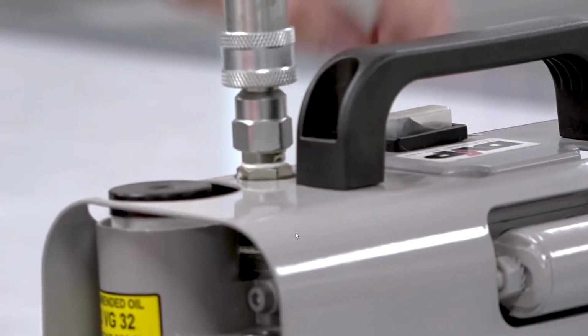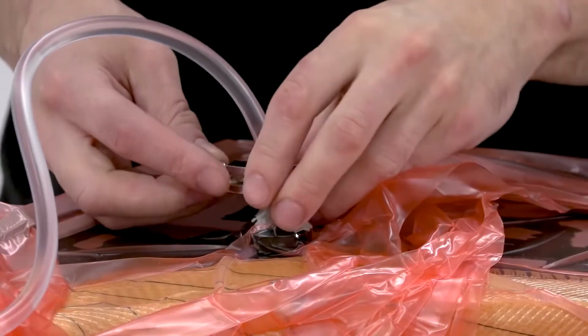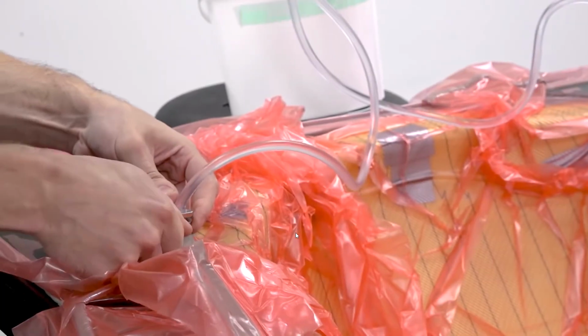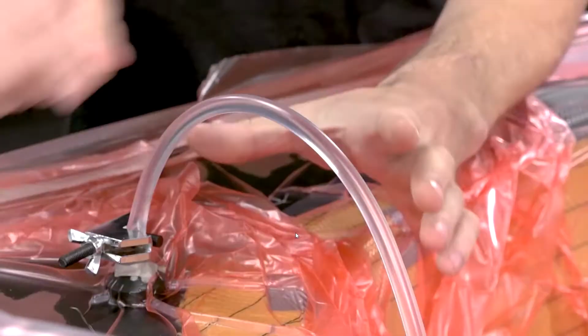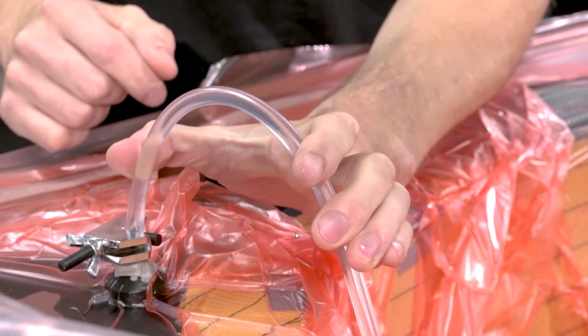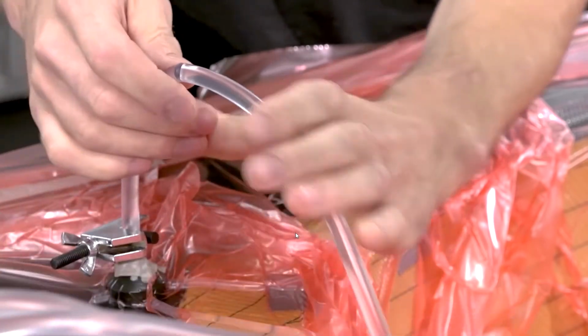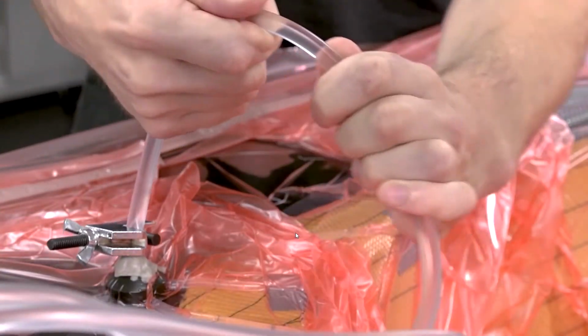Once fully saturated, the feed lines are to be clamped and the pump can be turned off. The part is then left to cure for the stated time and at the correct temperature found in the manufacturing guidelines. A way to check the resin is cured is by bending the feed hose. They should snap cleanly. If they bend, the resin hasn't set.